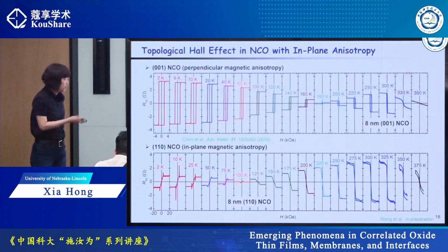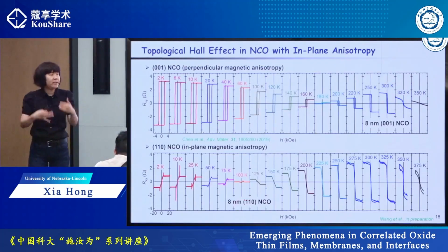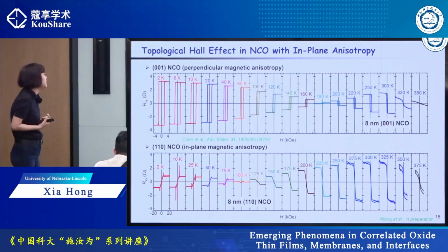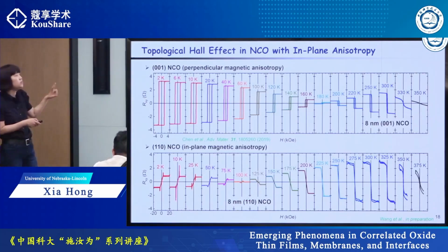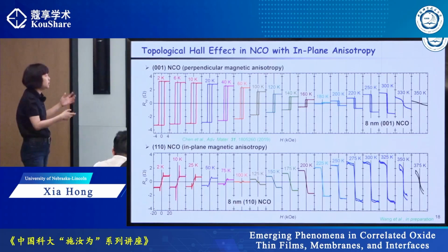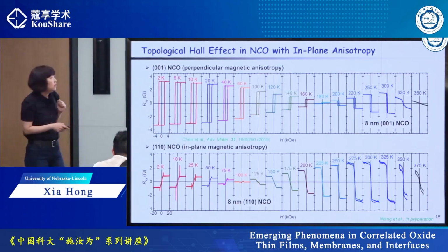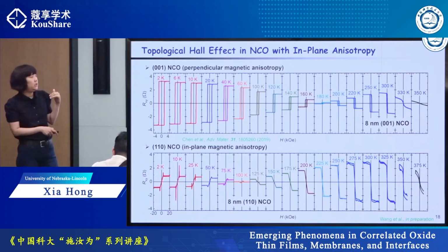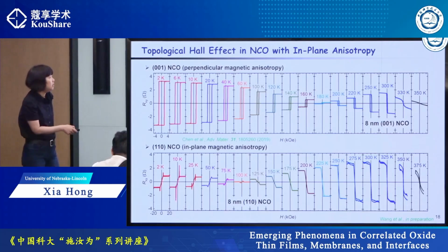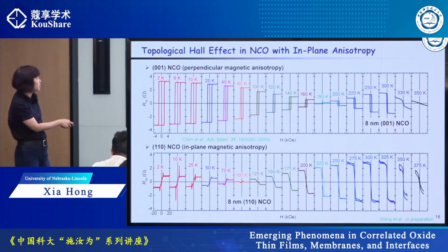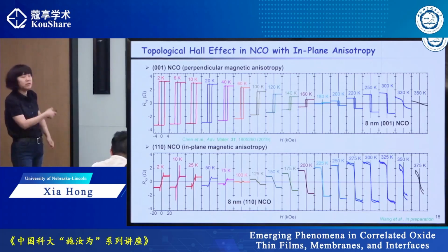Okay, so we actually see a signature in magnetotransport measurement that we may have this kind of chiral spin texture in NCO. Here I compare two films of the same thickness. One is 001. This is what I just showed you, and this one is the 110 direction. So first thing you notice is there's no hysteresis. This is because the magnetic anisotropy is actually in plane. So you have no hysteresis. You are just flipping the spin direction. And if you just trace the envelope of the amplitude, it's again non-monotonic. So you have this rise, it goes to 0 around 100K, and then it rises again, switches sign.